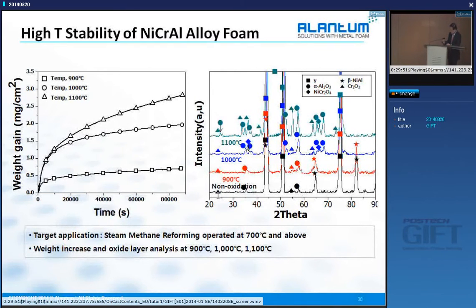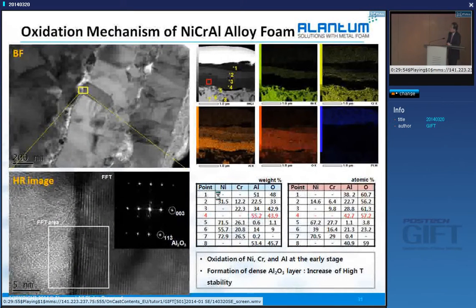Okay, let's continue. This is another interesting finding. You see the layers here, and then you see the elemental mapping or elemental analysis, like layer four, layer one. Layer four is another alumina layer. This is originally an alumina layer. Then through the sintering or the oxidation process, eventually alumina builds up more heavily on top of it. So this verifies that this form has some oxidation resistance. With high resolution, we can identify some other intermetallic particles.